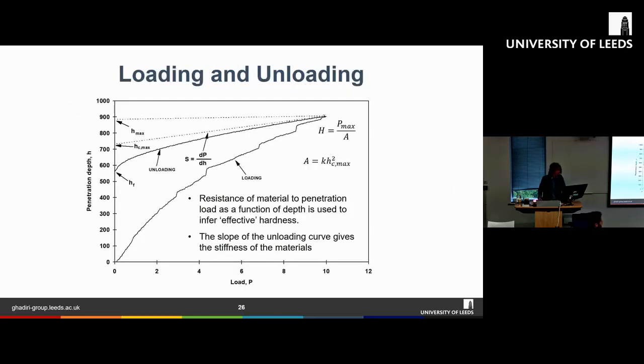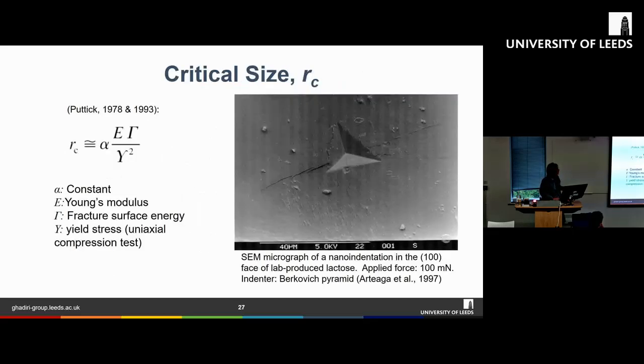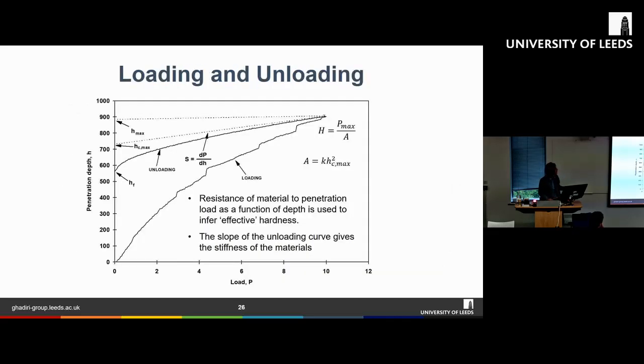Anyway, the maximum point here is where we measure the hardness of a material, essentially the maximum load that is experienced, and then you can use this correlation here. The correlation can easily be used to measure the hardness of the material, simply by dividing the maximum force by the indentation area, and the indentation area is given by this correlation here, where K is the indenter shape factor and h_c max is the maximum penetration depth.